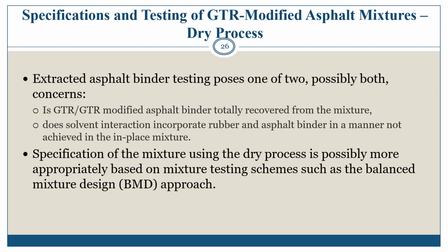Two concerns are posed with testing of extracted binder from GTR modified mixtures. One, is the GTR totally recovered from the mixture along with the asphalt binder? GTR is not totally soluble in any solvent due to SBR content. Two, does solvent extraction aid in better incorporation of the rubber and asphalt compared to the actual field performance? Balanced mixture design, or BMD, mixture testing schemes may be more appropriate for evaluation of dry process rubber modified mixtures.